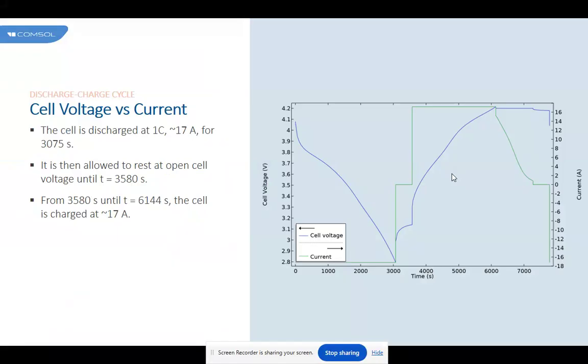The cell is discharged at 1C, about 17 amperes, for 3075 seconds. It is then allowed to rest at open cell voltage until t equals 3580 seconds. From 3580 seconds until t equals 6144 seconds, the cell is charged at about 17 amperes.